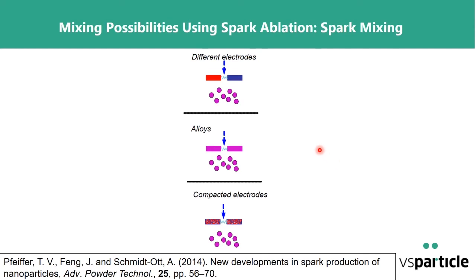Now, how do we mix? We have to form this mixed vapor in some way, and one possibility of doing that I already mentioned. That is using electrodes of two different materials, if it's just two components that we want to mix. Of course, each one of these electrodes may already be an alloy. The other possibility is that we make an alloy first, and the particles will consist of the same alloy. That's also a very important feature of the spark method. And it's due, again, to the high quenching, that the particle composition is always exactly the same as the composition of the electrodes.